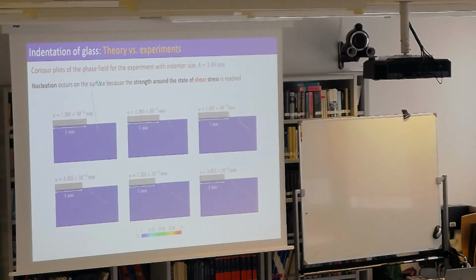So essentially what's happening, why this is nucleating there, is because the stress is hitting the strength surface around shear. So this has nothing to do with tension. This is shear from a macroscopic point of view. Of course, if I put a defect there, maybe it will be tension, right? But this is a macroscopic theory. We do not model defects explicitly. We have a strength that does that. The strength is essentially the macroscopic manifestation of defects. So this nucleates there because of shear strength.